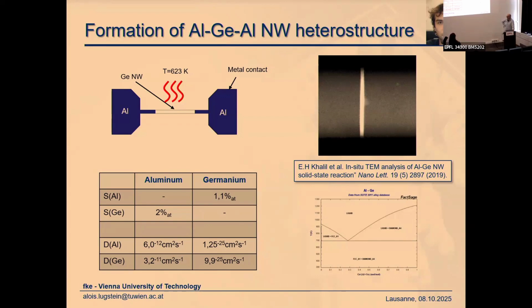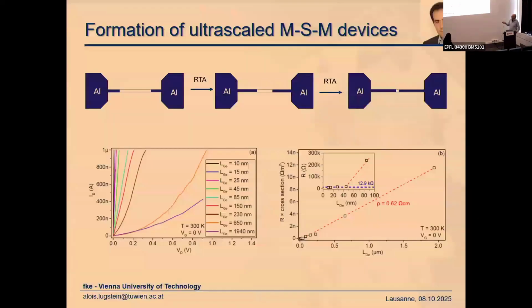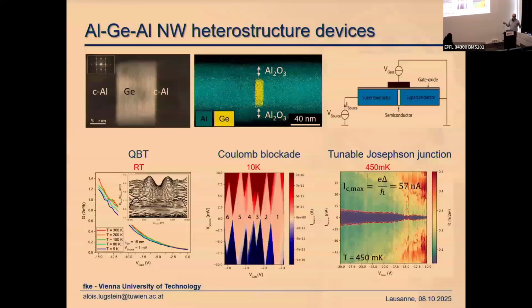Not the aluminum. No, happily the diffusion coefficients are so different. We tried to do all these experiments that I've shown here with a nickel approach or copper approach, but unfortunately they diffuse into the silicon and the germanium and they get completely contaminated. The nice feature of aluminum is that the diffusion coefficients are 10 orders of magnitude different. So the germanium or silicon segment is absolutely pure. It's huge, 10 orders. Yeah.